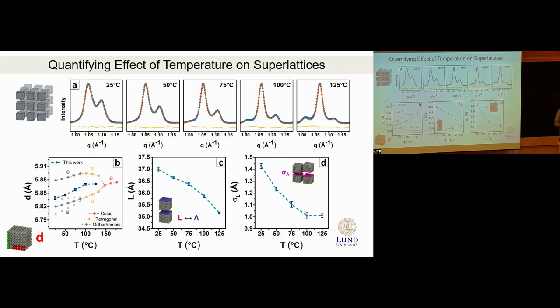What is your temperature ramping rate? I think it was 5 degrees a minute. So it should be basically at equilibrium at each data point. Yes, because then we reach the set point and sit for 15 minutes on it and record the patterns. And why do we sit for 15 minutes? Because in the preparatory experiments we collected more often to see when the sample stops changing.